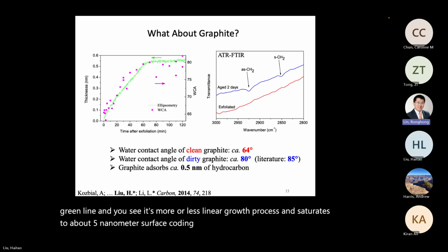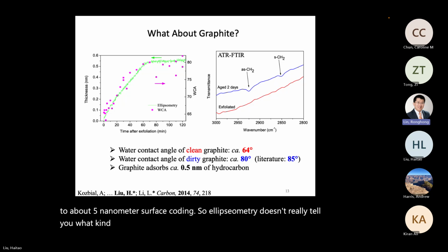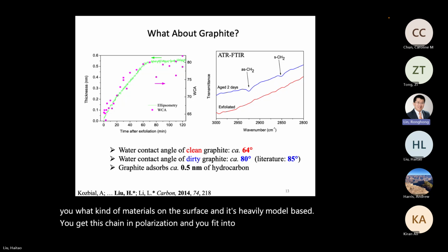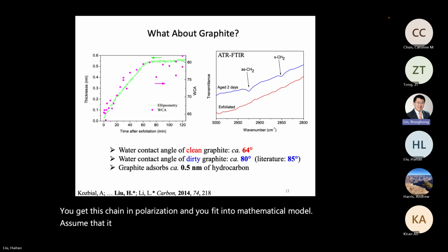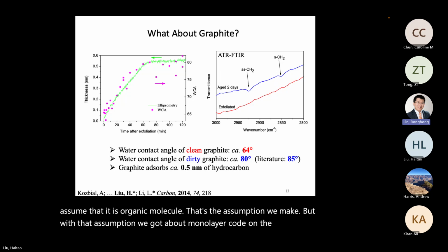So ellipsometry doesn't really tell you what kind of materials are on the surface, and it's heavily model-based. You get this change in polarization, and you fit it into a mathematical model, assuming that it is an organic molecule. That's the assumption we make. But with that assumption, we got about a monolayer coating on the surface, which more or less makes sense.